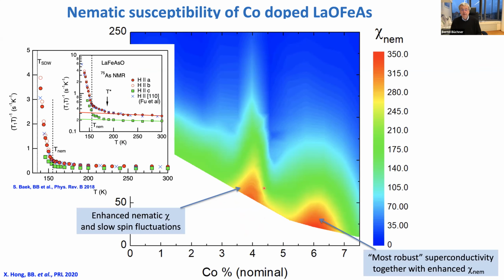And that there is a coupling, we know, of course. We know, for example, from NMR measurements, that when you go to the magnetic phase or the nematic phase transition, you see a strong enhancement of 1 over T1T, so a strong slowing down of spin fluctuations. So there is certainly a coupling between nematicity and spin fluctuations. And if the magnetic transition becomes very unstable and you enter close to the quantum critical point of the spin susceptibility, with an enhancement of spin susceptibility, you can also expect something going on in the nematic fluctuations. And that's what I think is going on here.